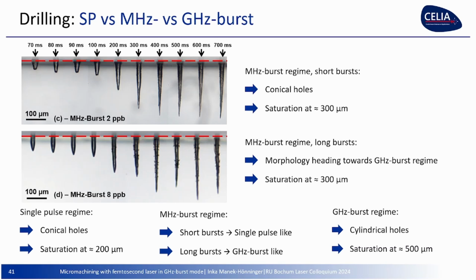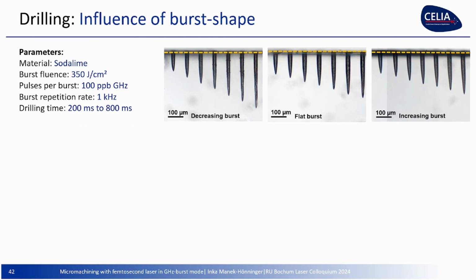So if you have a look on the influence of the burst shape, remember I talked about flat bursts, increasing and decreasing bursts, then you keep, of course, all the parameters the same, and as the laser system allows to have these different shapes, we don't have to realign anything. It's really comparable. This is also the advantage of having this 40 megahertz oscillator between the different regimes before as well. We don't have to realign. It's really the same alignment, so the comparisons are fair somehow, not due to a misalignment in the next experiment. When you have a look at flat burst, increasing burst, and decreasing burst, what can you see? Well, the holes are deeper in the decreasing burst.